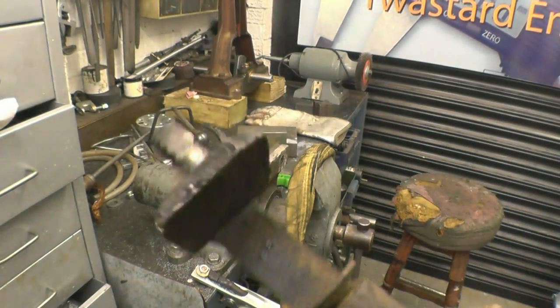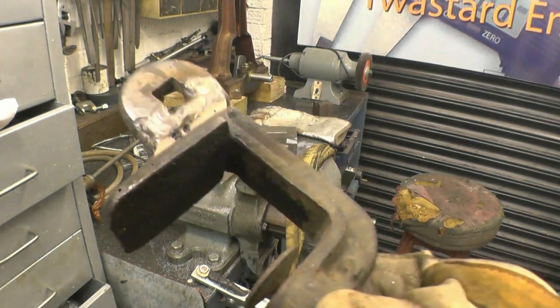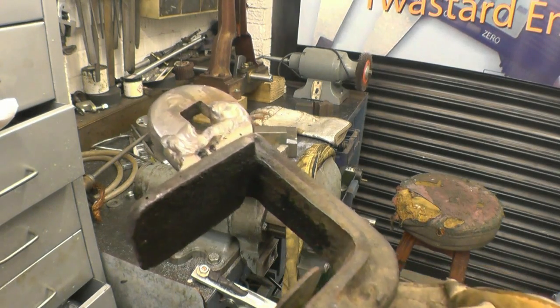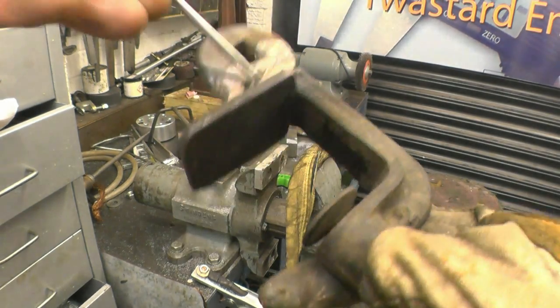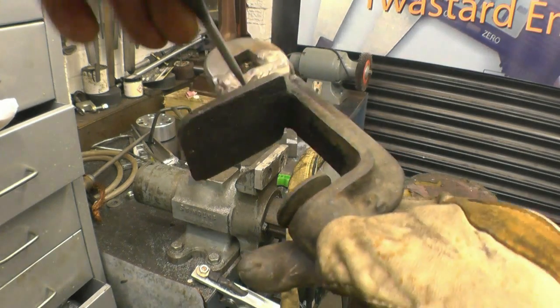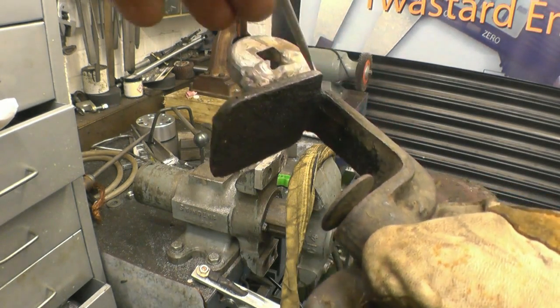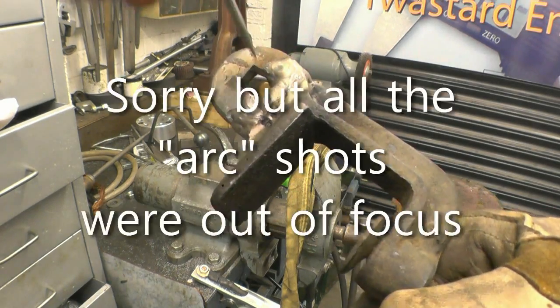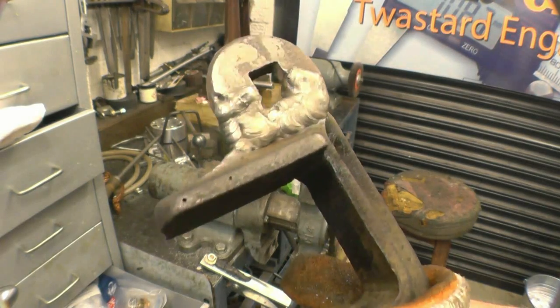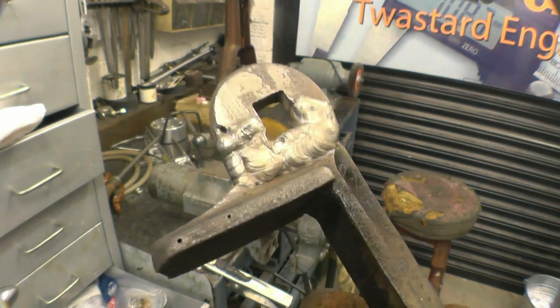Right, it started off welding not too bad, and then these appeared here. These are blowholes from the original casting. I don't know quite what's in there. I'll try and put some more weld along there, but the actual cracks welded up quite nicely. Right, it's actually built up quite nicely with a stainless weld.